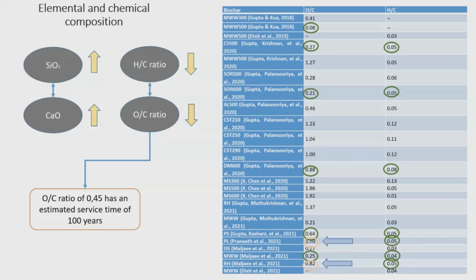This is highly dependent on thermochemical conversion temperature, because the higher this temperature, the more carbon content, and thus a lower OC and HC ratio. In these studies as well, the highest HC ratios correspond to the lowest temperatures, indicating a less aromatic biochar. In other words, less stable carbon in biochar. So, one of the solutions to obtain a stable biochar for use in cementitious composites would be to increase the thermochemical conversion temperature. And this has been evidenced by an absorption mechanism shift from cation exchange, CEC, to physisorption, affecting its absorption capabilities as well.